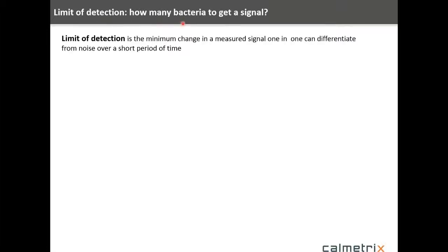One question that comes up in many cases is, well, how many bacteria does it take to get a signal? Really what we're talking about is the limit of detection, which is the minimum change in the measured signal that you can differentiate from the noise over some period of time. In our instruments, we have a limit of detection of about 5 microwatts in a well temperature controlled lab. So in a typical microbiological lab, where you have good temperature control on the order of plus or minus a tenth of a degree C, then you're going to get this kind of level of limit of detection. It really has to do with the baseline noise, and so our limit is about 5 microwatts.